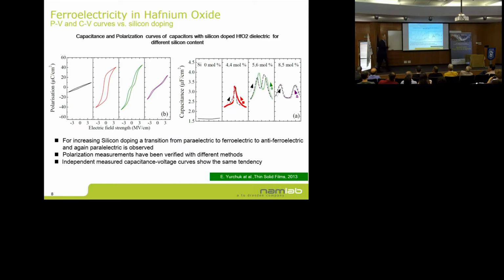What he observed, at certain concentrations of silicon that he added, was that he all of a sudden got peaks in the CV curves, and they went to very high capacitance values. He was interested in that because he was trying to increase the K value for the DRAMs. He looked closer, and when he measured polarization, he found that he got very nice hysteresis loops. And for some other concentration of the dopants, he got antiferroelectric hysteresis loops.